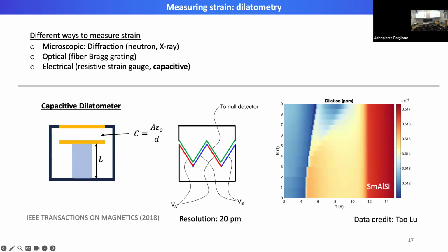And in our lab, we have a commercial capacitive dilatometer. And the idea of the experiment is really simple, where you have your sample here that's shown as the blue block here. Right. And if there are metal plates that are movable together with the sample, we will be able to deduce the length change of the material from capacitance measurements. Right.